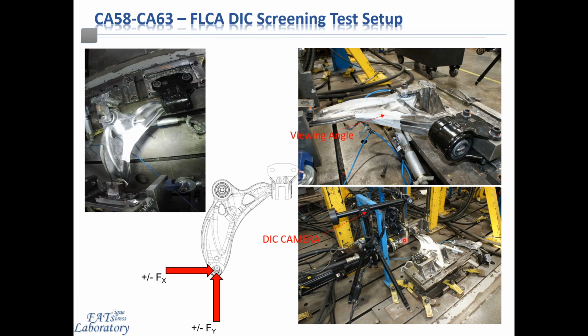Once the forged components were actually made, we subjected them to a series of fatigue tests to satisfy the durability requirements which the automotive manufacturer mandated on a fully instrumented load frame with biaxial load actuation. You can see here a video on the left of the physical test being conducted, with a schematic of the force vectors being subjected to the component shown in the middle here.